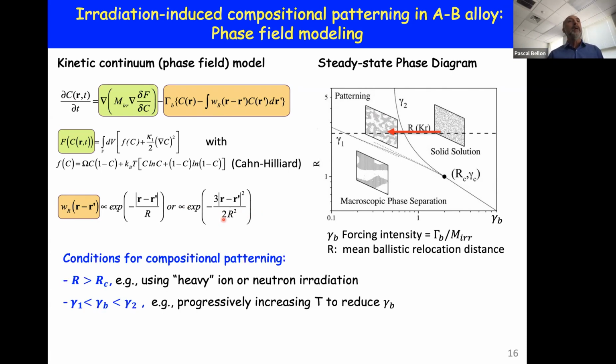And so the idea is that what we've seen now using that phase field model is that R needs to be greater than RC, or critical radius distance, to trigger self-organization. And this self-organization only takes place in a range of forcing intensity. So if you drive the system too hard, you dissolve the precipitates. If you do not drive it hard enough, the system will revert to macroscopic phase separation. So you have to find this sweet spot here for patterning.